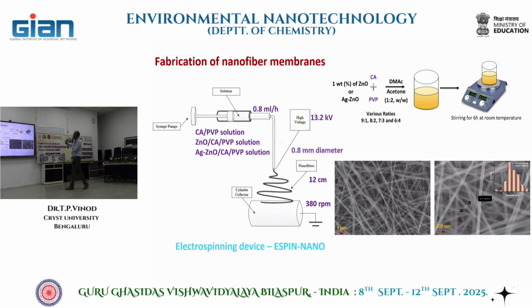The plan is like you mix all these materials which are giving you these properties. So we worked with a polymer mixture which is actually cellulose acetate and polyvinyl pyrrolidone. Into that we incorporated zinc oxide particle and also silver doped zinc oxide particle. Three different systems we studied. The polymer solution is a mixture of either this or this. Okay, CA means cellulose acetate, PVP means polyvinyl pyrrolidone. So certain polymers, they are not spinnable, but to make them spinnable, you need to mix it with another polymer. So that's why we mix this PVP and cellulose acetate, and these are the optimized conditions.